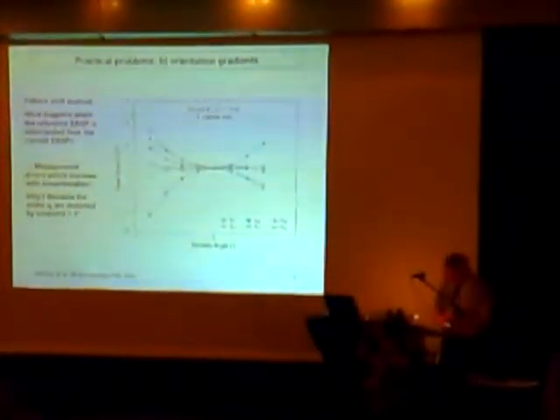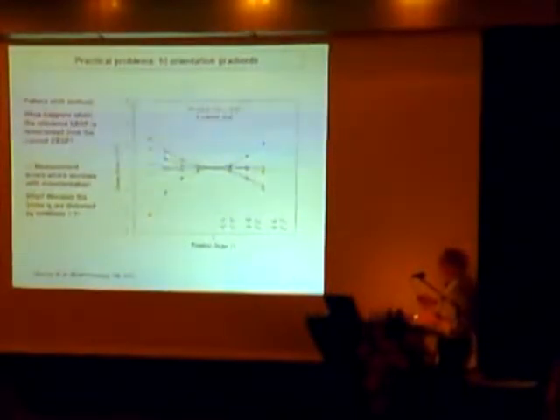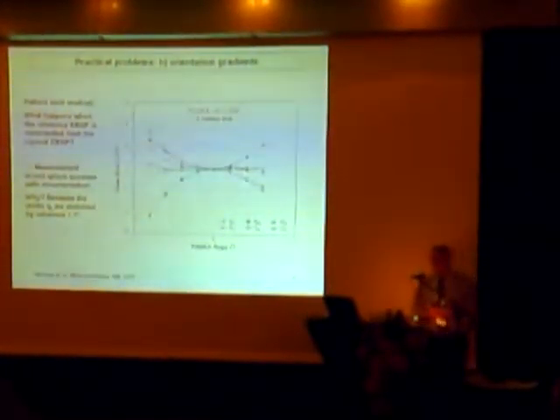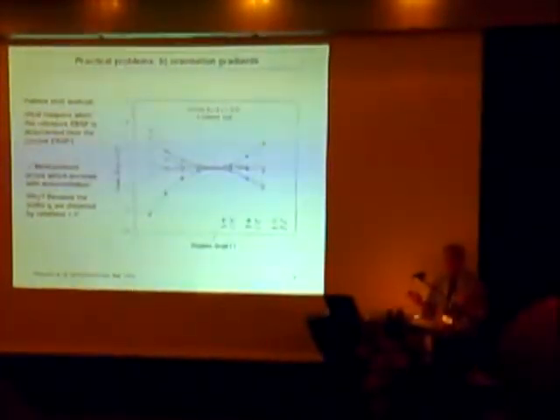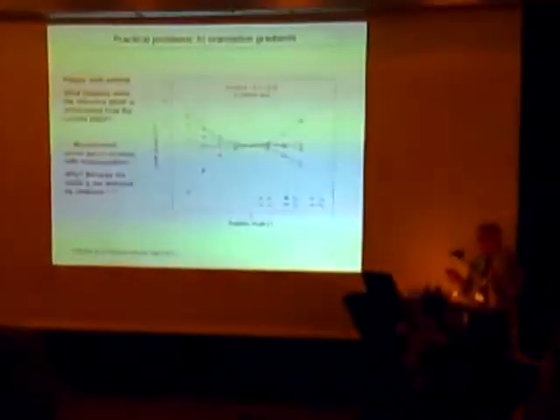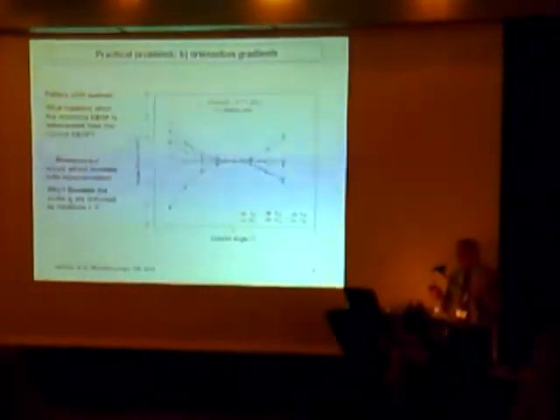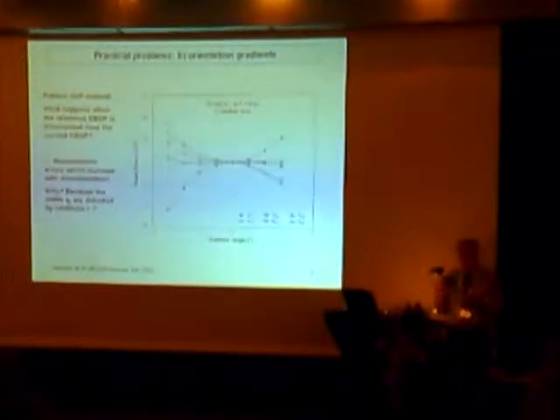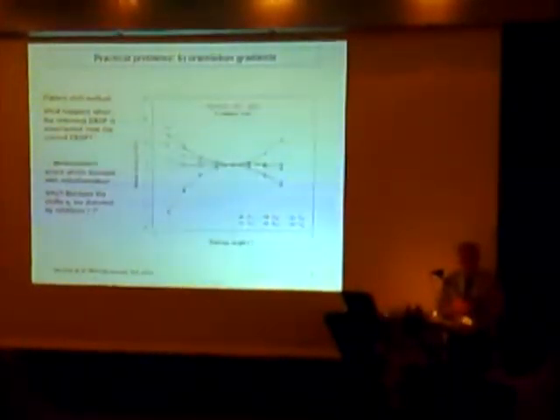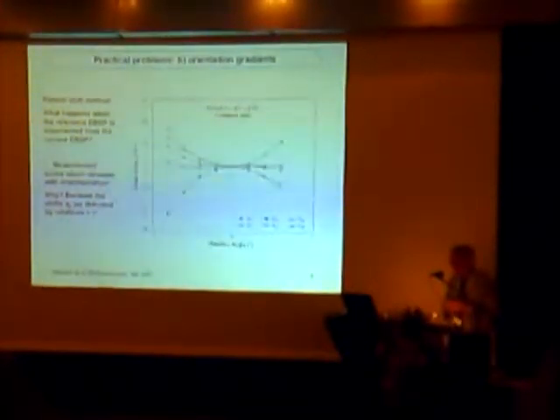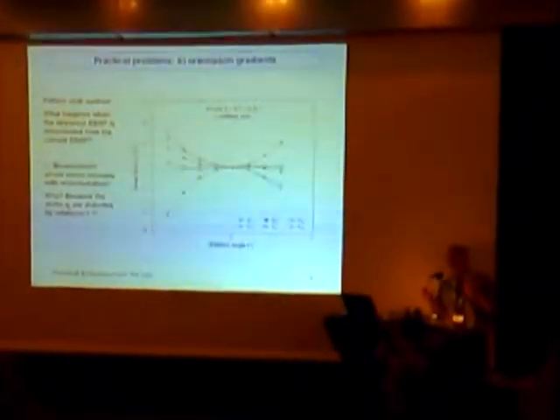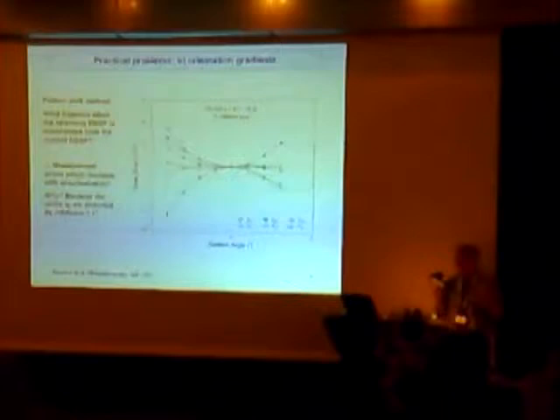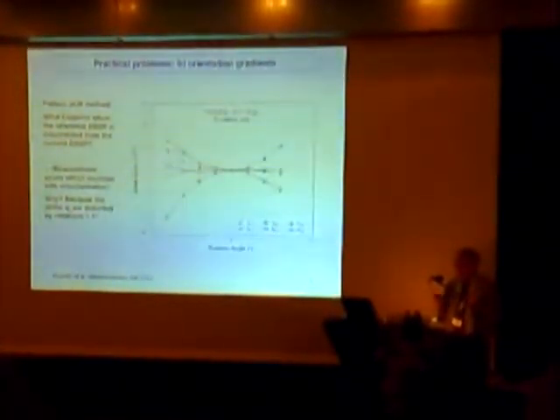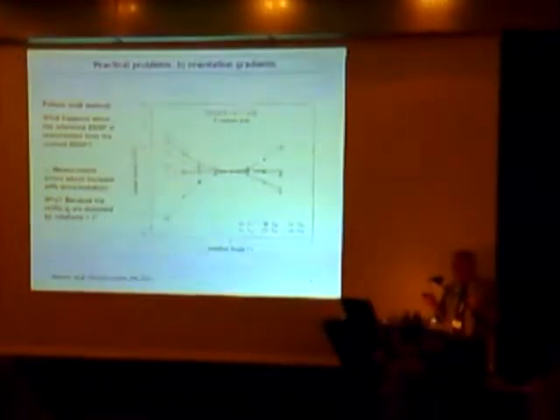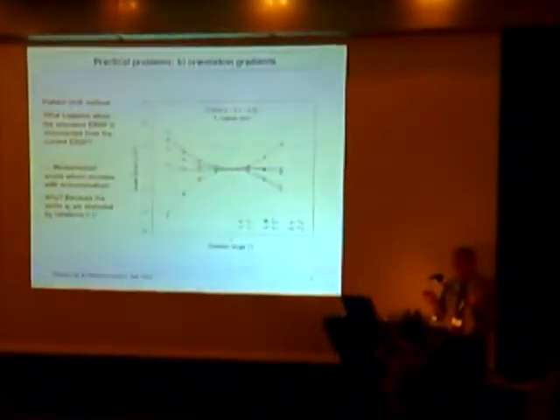Then the second problem is what we call the problem of orientation gradients. If you have a perfect single crystal, then you don't have any orientation gradients. But if you're looking at the more interesting samples, which have got dislocations and subboundaries and things like that, they have orientation gradients, typically a few degrees. Now, in the initial work, when people compared the pattern shifts on the sample with the reference, people thought that any orientation difference between the reference and your current sample area had no influence.